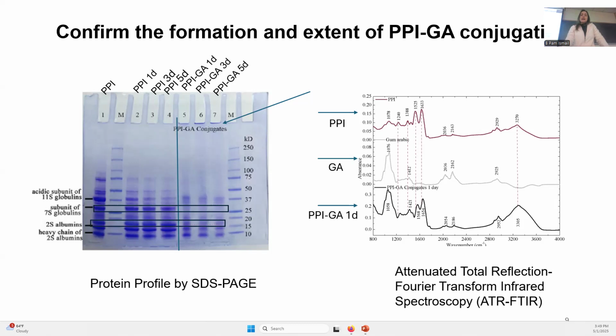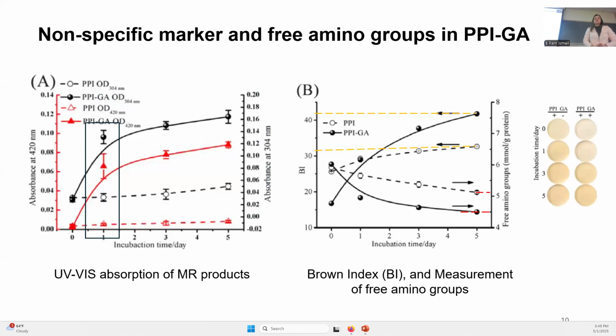They also looked at the FTIR, and the appearance of new bands was an indicator that Maillard products were forming. Then they also looked at non-specific markers and free amine groups to determine the extent of the glycation, the conjugation. In graph A, we're looking at the UV-vis absorption that was used as a non-specific marker. The absorption was measured at 304 and 420 nm. The 420 was attributed to the formation of brown components.